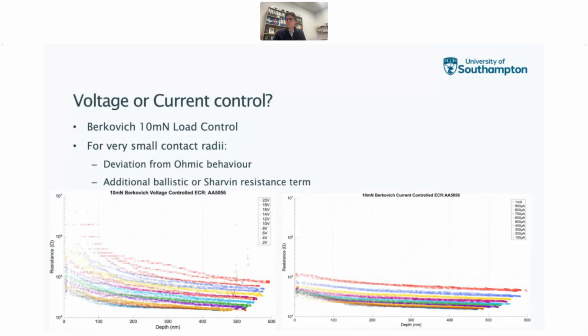Now, which should we use, though, when we come to actually do the measurements? Should we do voltage control or current control? To answer this, we've used a Berkovich indenter and inserted it into our aluminium alloy, up to 10 millinewtons. And then we've measured either in voltage control, where we've specified an upper limit of a milliamp at different voltages.